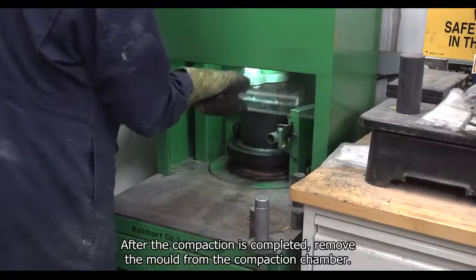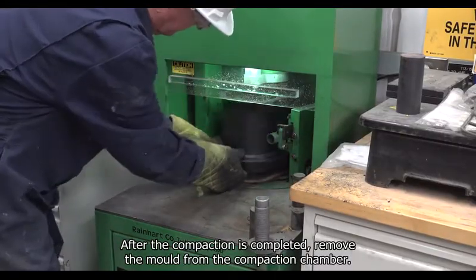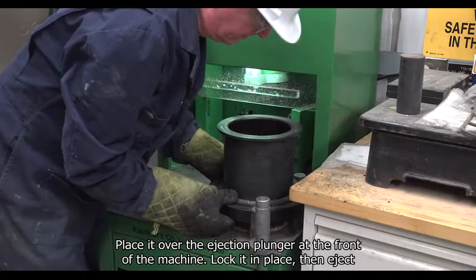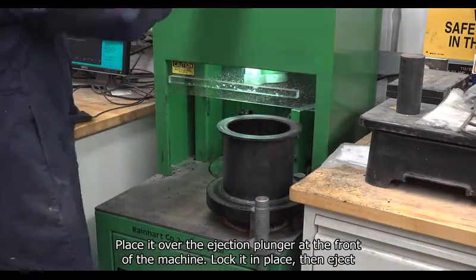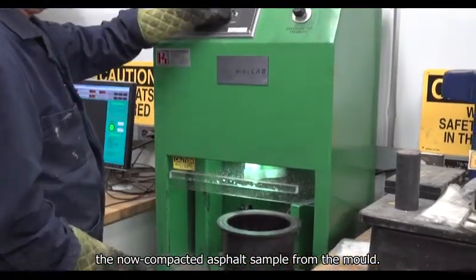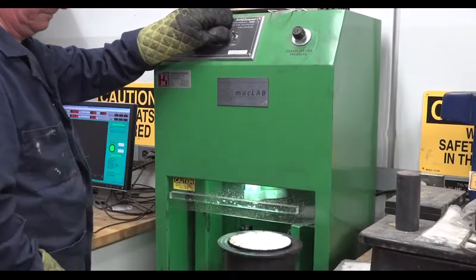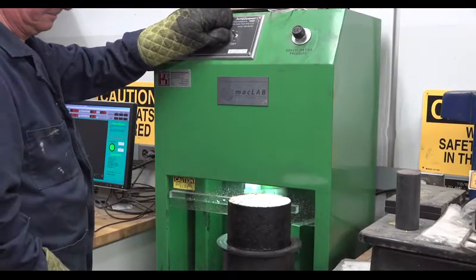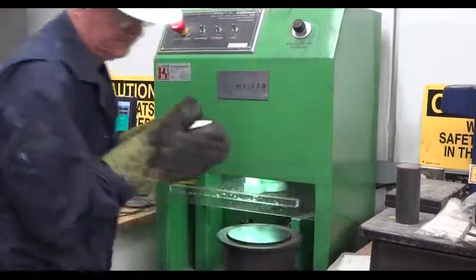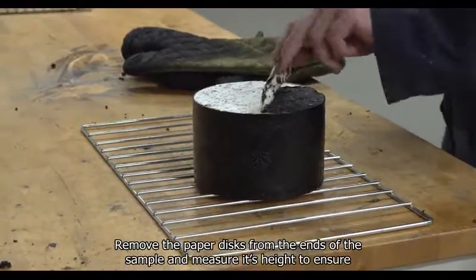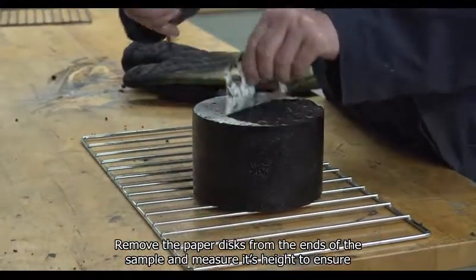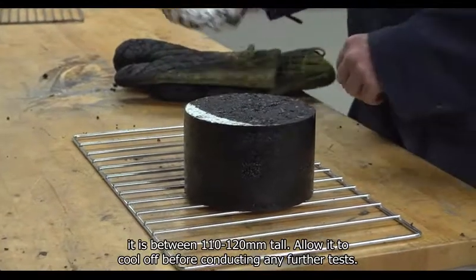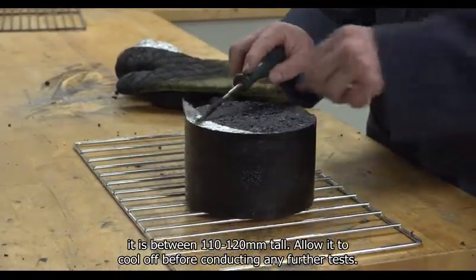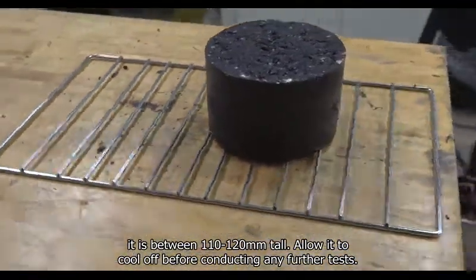After the compaction is completed, remove the mold from the compaction chamber. Place it over the ejection plunger at the front of the machine. Lock it in place, then eject the now compacted asphalt sample from the mold. Remove the paper discs from the ends of the sample and measure its height to ensure it is between 110 and 120 millimeters tall. Allow it to cool off before conducting any further tests.